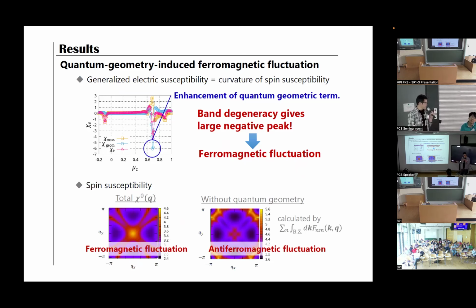On the other hand, when we neglect the quantum geometries, we obtain the spin susceptibility like this, in these figures. So we see that the ferromagnetic fluctuation disappears, as we see the large peak around pi. So this rather means anti-ferromagnetic fluctuation. So this means that the ferromagnetic fluctuation is induced by the quantum geometry in this case.